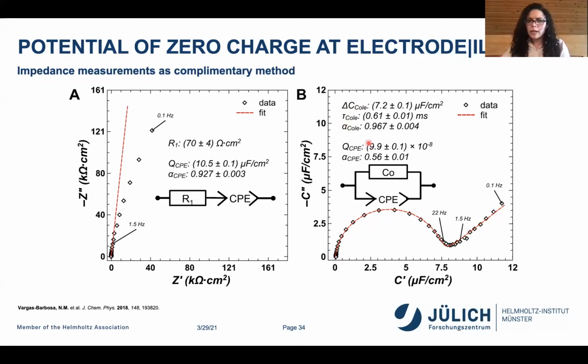And so when we look at this, we got this, and then we have this tail again at lower frequencies, which we still don't know what it is, and because we don't know what it is, we just fitted it with a constant phase element. I'll come back to that in a little bit. But the reality is, in doing this kind of fit, we obtain very similar data, because here the diameter of the semicircle is about 7 microfarads, and the capacitance that we would get from the other fit is also in the same order. And the ideality parameter is also similar, so it's kind of complementary data.